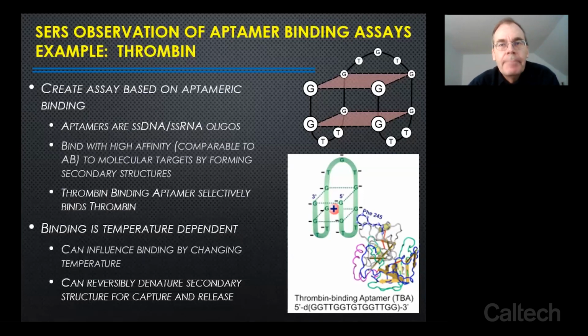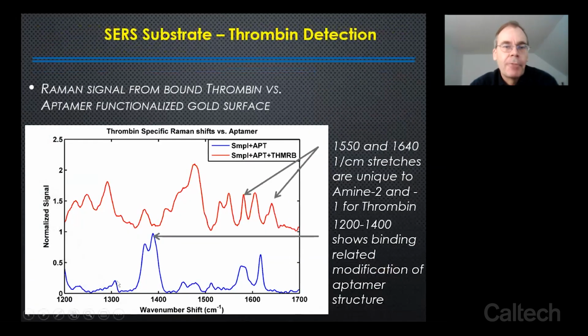And so fortunately, there is what's called a thrombin binding aptamer that allows us to selectively coat on top of our surface enhanced Raman spectroscopy nanobulbs, these gold particles. And we can then measure spectroscopically the thrombin that way. And so what happens is if we take this thrombin binding aptamer and we measure that in our surface enhanced Raman spectroscope, we actually get this kind of blue spectrum when we look at the scattered light, the Raman spectrum. And then when the thrombin binds to it, you get this red spectrum. It's fundamentally different. It has these different vibrational modes that occur when one material binds to another. So you actually can see the reaction of thrombin onto the thrombin binding aptamer right in real time.